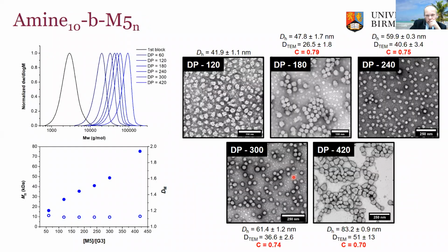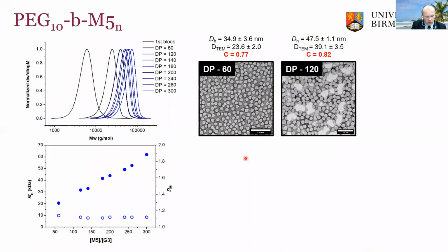So if we just look at the system where we have our amine block, you can see from the SEC traces and data, we have a well-controlled polymerization producing relatively narrow dispersity polymers. If we run through the DPs, increasing DP from 120 through to 420, you can see the particles increase in size from about 40 nanometers to about 80 nanometers. The circularity stays relatively similar, about 0.79, 0.75, 0.74. They're very similar. You can see these start to look a little bit elongated. So we're just seeing spherical constructs throughout, and vesicles throughout the whole range, even at really rather high DPs.